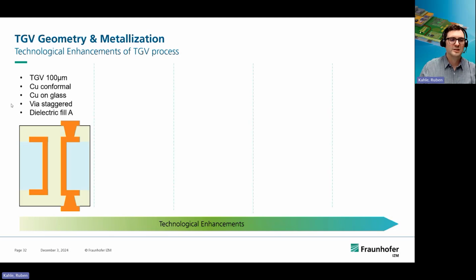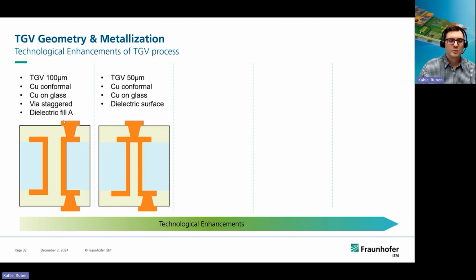We've seen copper was plated directly on glass. It was done conformal. We were far away from filling it, for example. And we simply use the dielectric that you need for the RDL to fill these holes. Next step was done by doing it in a way that you at least close one side of the TGV, so you can lower the TGV diameter. That was done at the same time. All of these LIDE processes came up. And this was one of the brilliant moves in R&D and the academic world that we found, not we as Fraunhofer, I mean we the academic world, we found that you can modify glass with a laser, and then you can etch it. And this was really a great breakthrough. So from one point to another, you can create really, really great TGVs.